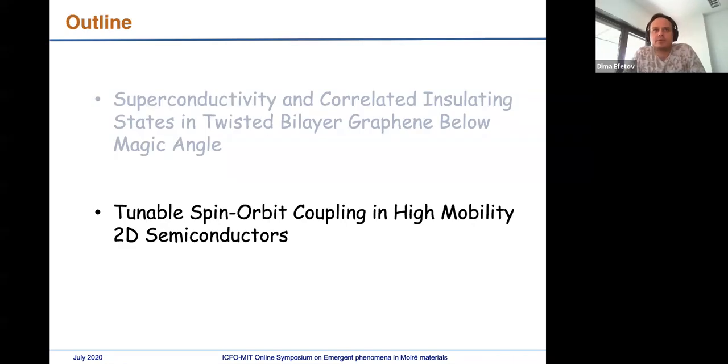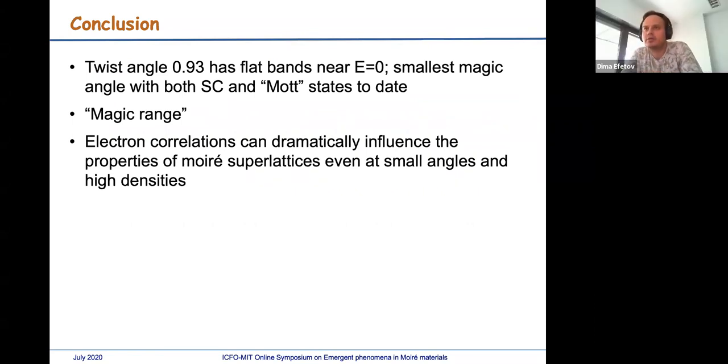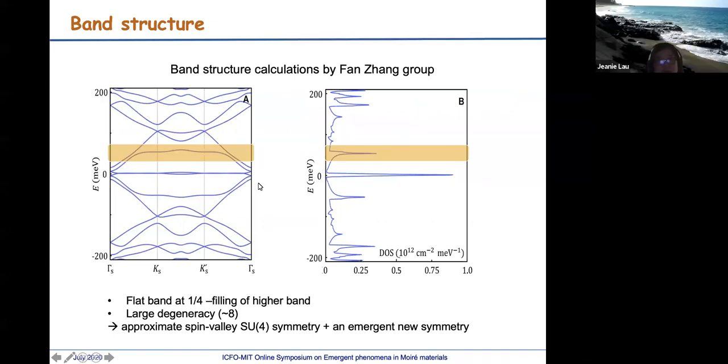Okay, Jenny, we have a couple of questions. The first question is, can you explain why the second Dirac point on the right side is much more intense than on the left side? So basically electron-hole symmetry. Well, again, I did not do the calculation, but I believe it comes from the fact that it's not super asymmetric, but there's a slight asymmetry that comes from the electric field that will break the electron-hole symmetry. This is a single-gated device, so we have only a back gate, and when you dope the device, it also introduces an electric field.